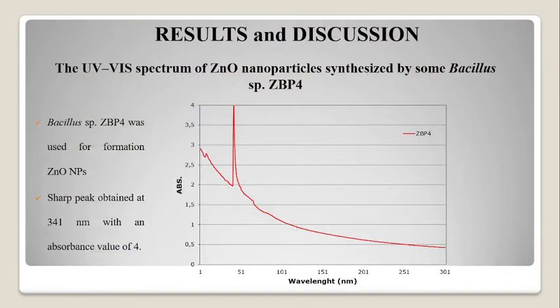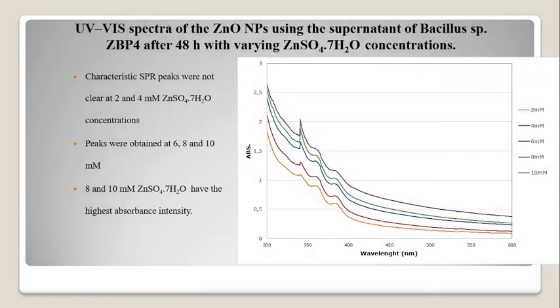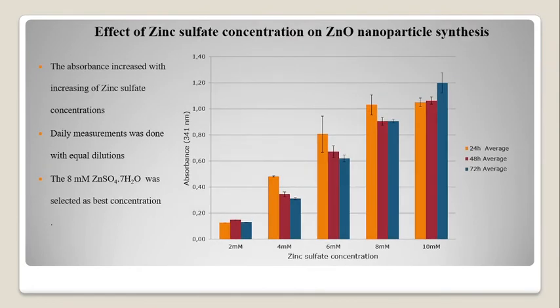Results and discussion. The sharp peak was obtained at 341 nanometers. This is a figure that shows the different concentrations of precursor, zinc sulfate heptahydrate, and the sharp peaks were obtained at 6, 8, and 10 millimole. This is a figure that shows the effect of zinc sulfate concentration on zinc oxide nanoparticles. The 8 millimole zinc sulfate heptahydrate was selected as the best concentration for the second and third days.